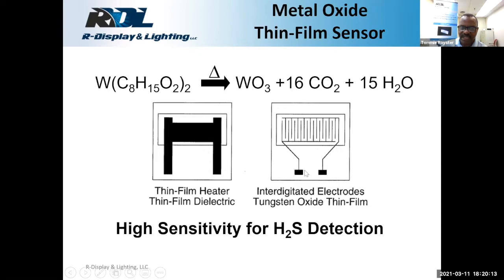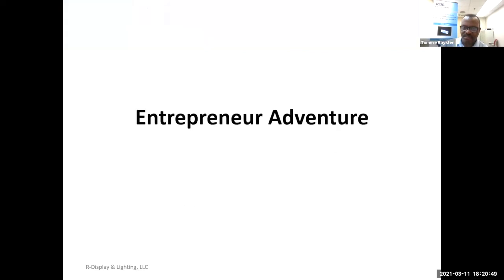And we were able to establish a strong correlation between voltage output of these interdigitated electrodes and the concentration of hydrogen sulfide that was expanded into a vacuum system which housed the thin film solid state sensor. And the important study showed that the microstructure was the key to increasing the sensitivity. You need to have an amorphous film. Crystalline films were not very sensitive. Okay, so that completes the Eastman Kodak study.